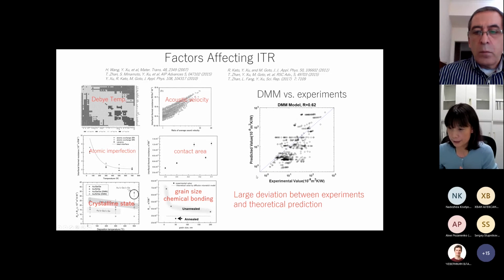Here I show the comparison between a physical model's prediction and the experimental value. DMM is the most commonly used physical model for predicting ITR. If we take the DMM prediction as the vertical axis and the experimental value as the horizontal axis, we can see that the accuracy actually is not very high. So there is a large deviation between them. So we feel that it's difficult to have a physical model to predict ITR.